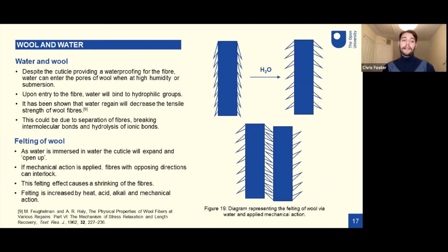If then mechanical action is applied, fibres with opposing directions can actually interlock, as seen in figure 19. And this felting effect can cause fibres and the whole textile to shrink, and it can be quite significant. This felting process is increased by heat, acid, alkali, and also it increases with increasing mechanical action. So the more mechanical action you use, say, for example, sponging, the more felting that can occur.